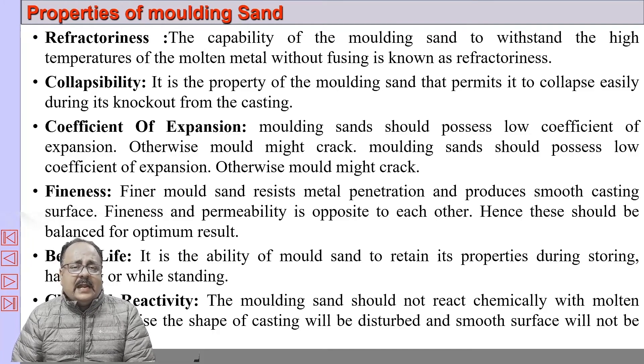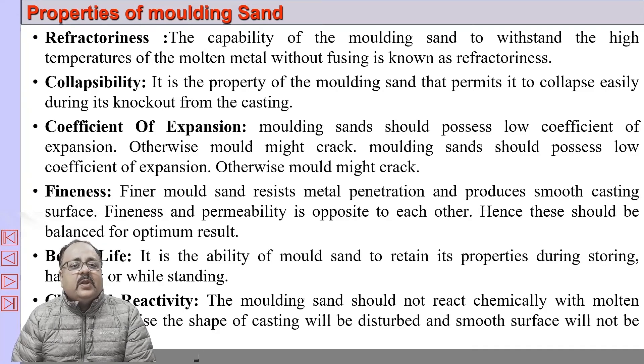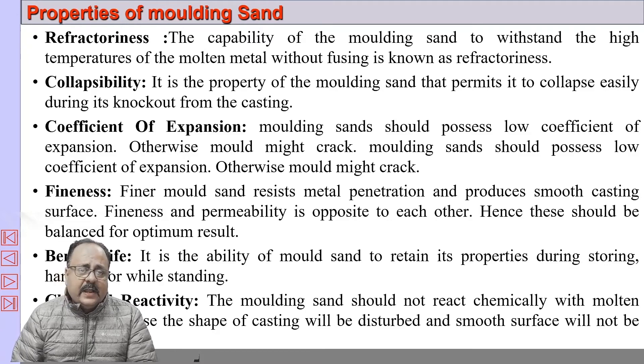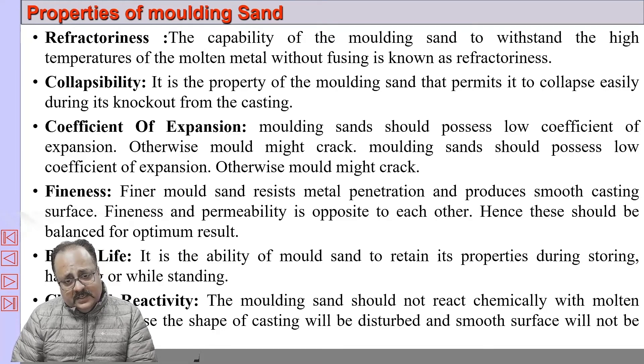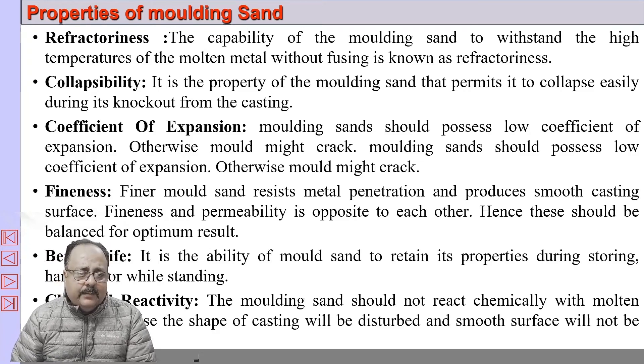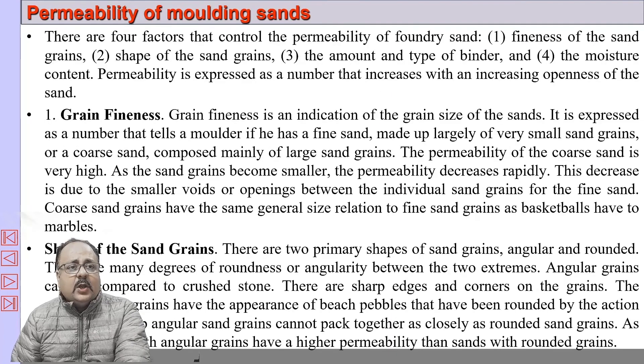Collapsibility: the mold must be broken after casting so the casting can be taken out; if the sand becomes too hard, it is difficult to break the mold. The molding sand should also have a low coefficient of expansion, otherwise the mold might crack. Fineness: finer sand improves surface finish but decreases permeability, so there must be a balance between fineness and permeability. Bench life is the ability of the molding sand to retain its properties during storing, handling, and standing. The molding sand should also not be chemically reactive.